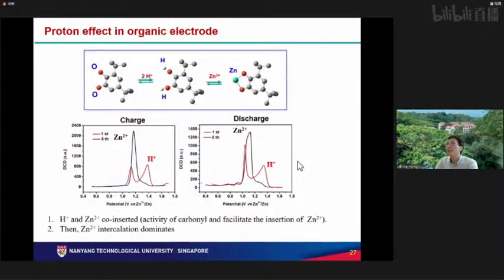Okay, and actually, if we do organic cathode materials, we also borrow all the concepts from inorganic. We know that for vanadiums and manganese, we have protons in and out, right? Proton insertion is a very common phenomenon in the manganese oxide tunnel structures. Sometimes the proton may have a conversion reaction first to change the crystal structures. We find that even in organic cathodes, the proton may also go in and out and interact with the functional groups. For example, in the first step, the proton goes in and forms a bond with oxygen, and later on the zinc comes in.